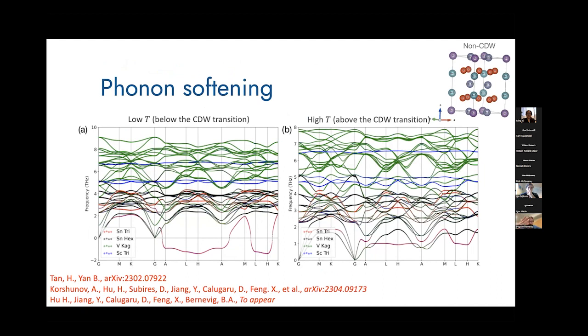And these high temperatures are very, very high temperatures for the CDW, but basically they give you the phonon spectrum supposedly in the non-CDW phase. So on the left is low T. You can see a clear negative phonon on the entire plane around k equals pi, with a minimum at the H point, but it's a soft minimum.